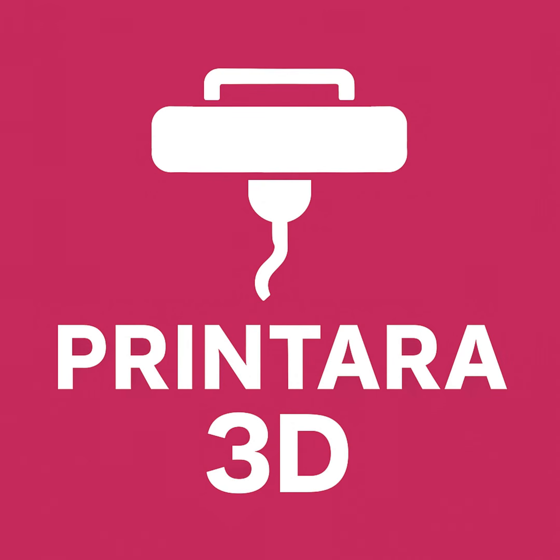Yeah. Poor layer bonding, visible bubbling or hissing as the water boils in the nozzle, maybe even steam. And ultimately, your prints will be weak, brittle, and just generally awful. So it completely negates the whole reason you chose nylon in the first place if it gets wet. Precisely. So it must be actively dried before you print it. And ideally, kept dry during the printing process, too. People often use dedicated filament dryers, which are basically heater boxes, for materials like nylon. Okay, so it sounds like a material that really rewards careful preparation and handling. You can't just leave it lying around.